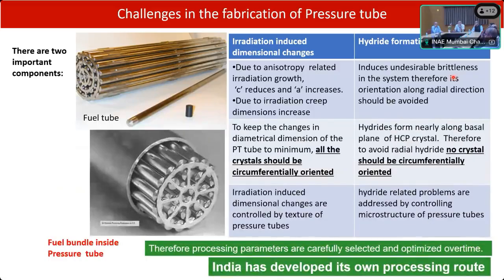But the problem with zirconium is that it is a highly anisotropic material. The second problem is that it has a lot of hydrogen-related issues. It has very low solubility for hydrogen and immediately forms a brittle phase, so the entire mechanical property of the zirconium alloys gets compromised. As a consequence, you have to give a very, very specific orientation to the grains of the crystal structure so that you can mitigate that.